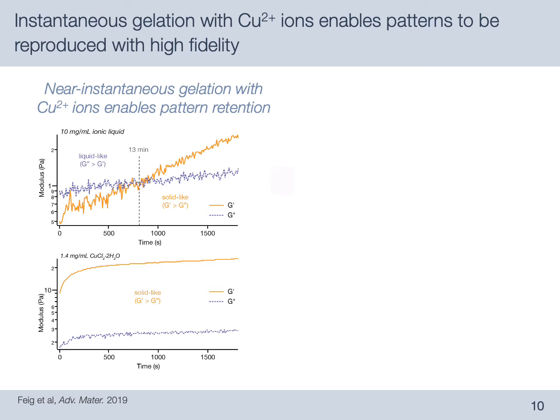Here again, gelation kinetics play an important role. Compared to the ionic liquid, gelation of PEDOT:PSS in the presence of copper ions happens nearly instantaneously, such that we cannot even see a crossover on the rheometer, which is shown on the bottom left here. This allows the sacrificial metal pattern to be transferred to the resulting hydrogel with high fidelity, because the ions do not have enough time to diffuse away from the surface before gelation occurs.